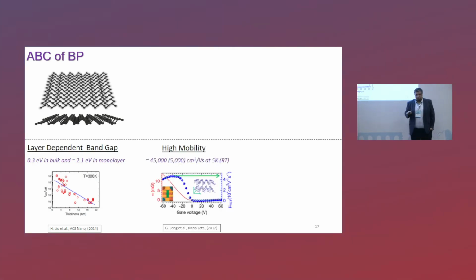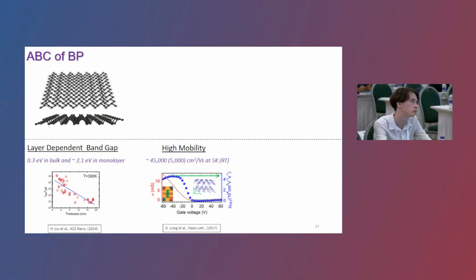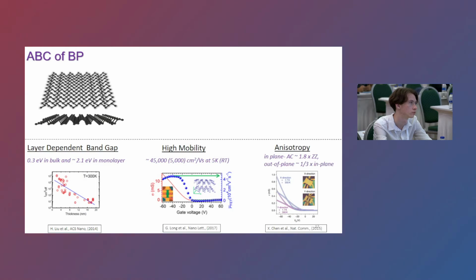But typically, you would expect quite low mobility for semiconductors compared to graphene, of course. But the mobilities that we are measuring in black phosphorus are quite high. Indeed, it's even approaching 50,000 cm squared per volt per second at low temperature. So this also makes this material quite interesting for us.